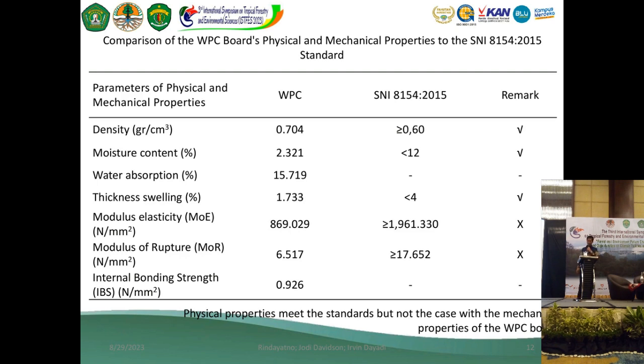We try to compare with the Indonesian standard, SNI 8154:2015. And the result is that physical properties meet the standard, but not the case with the mechanical properties. Because they are related to the level of load that WPC board can support, the mechanical properties of WPC board are given priority for evaluation as a requirement for a structural application. Data in the table indicate that the WPC board has not yet satisfied the standard.